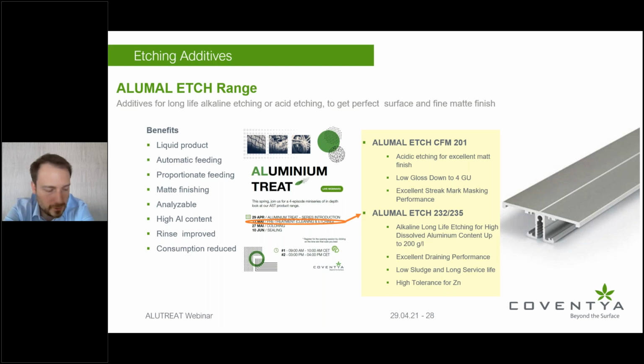Or even, which is what we will focus on more extensively today, because the classical caustic etch is very dependent on the alloying elements and their distribution, it is an issue to use secondary aluminum. Whereas with this acidic cycle beforehand and their combination, one could utilize many different alloys and even secondary aluminum without any drawback in terms of aesthetical performance.